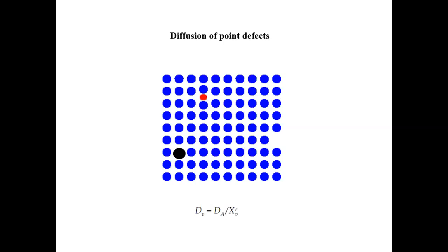So this explains the difference of the apparent diffusivity. Because when we talk about diffusivity of an atom, you have to focus on a particular atom, focus on this guy. Say I can use radioactive or some other tracers to keep track of this atom, right? And it is involved in the motion of the vacancy only once and it's going to stay there. So if I keep track of this atom, I have to wait until the next vacancy comes nearby and it can move. So it will move much slower, but the vacancy is moving all the time.